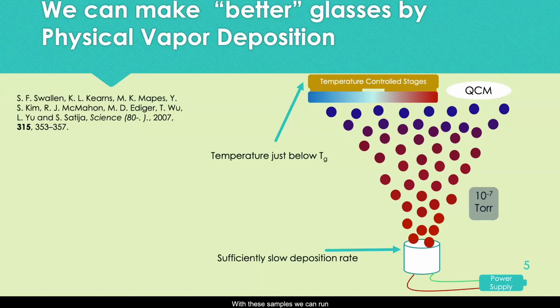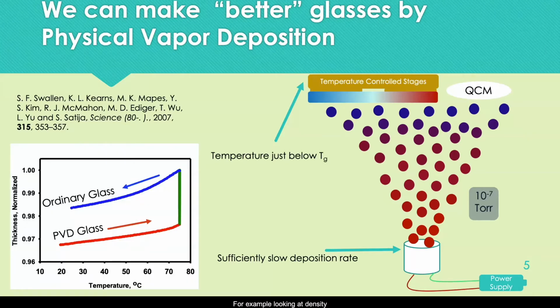With these samples, we can then run various experiments and observe particular properties, including high kinetic stability or high density as compared to liquid quenched glasses. For example, looking at density, we might deposit a physically vapor deposited glass, look at its thickness, and then heat it into the supercooled liquid, and then cool the supercooled liquid back down into an ordinary liquid quenched glass. And as you can see, the liquid quenched ordinary glass has a higher thickness, therefore a lower density than the PVD glasses, and we can compare the before and after thickness to get a relative density change, typically maximizing around 1-2% relative to the ordinary glass.